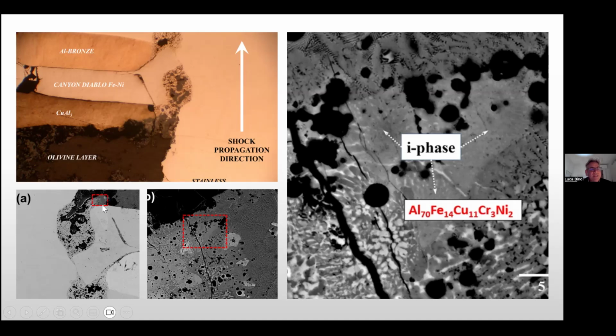Look at the red rectangle here, because it is blown up here and then again here on the right. And with our measure surprise, at the very first shock, we produced an icosahedral phase with a composition very close to that of icosahedrite if you neglect the chromium and nickel content. At the beginning, we understood that we produced an icosahedral phase by means of electron backscatter diffraction.